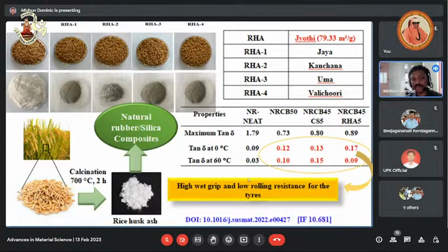Suppose we burn rice husk at a very high temperature, around 700 degrees Celsius, for 2 hours. We get rice husk ash, which has 90% silica. Rice husk ash is a rich source of silica. So we collected 5 different varieties of rice husk, namely Jyothi, Jaya, Kanchana, Uma, and Valichuri.